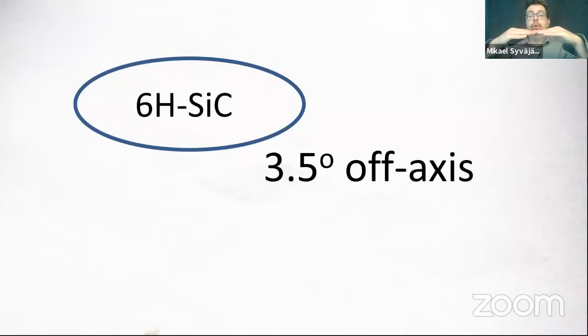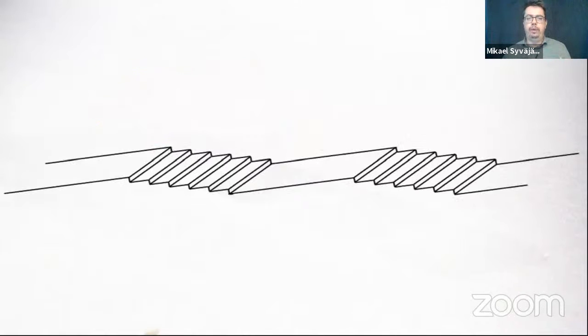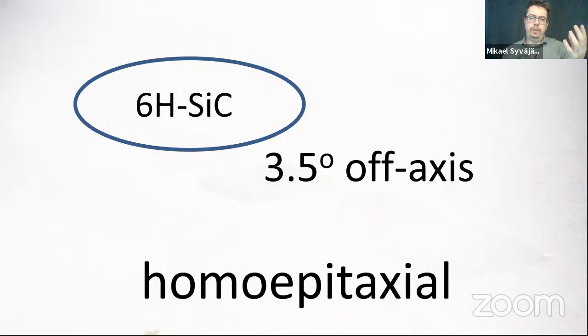So what the community was doing was to change to 3.5 degrees off-axis, and then there were no cubic silicon carbide inclusions. Very good. And then the community started to control the 4H silicon carbide, and this is a little more attractive for power devices than the 6H silicon carbide. And by the off-axis, when you create that one, then you have these steps which are growing layer by layer and building up, and you replicate the substrate polytype. So that was achieved for 6H with 3.5 degrees off-axis, and you have 6H layers on the 6H wafer.